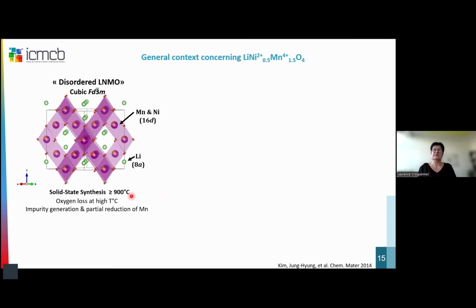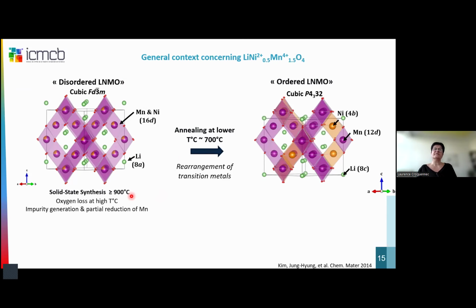We'll come back to that later. And we have a second structure for these LNMO that is also cubic. And when we reanneal these materials at lower temperatures, 700, we have a rearrangement of the transition metals, I would say, within the samples. And in that case, the pure phase can be obtained with ordered structures, with nickel in octahedral sites, only nickel 2 plus in that site 4B, and then manganese in the other sites, 12D octahedrals also.